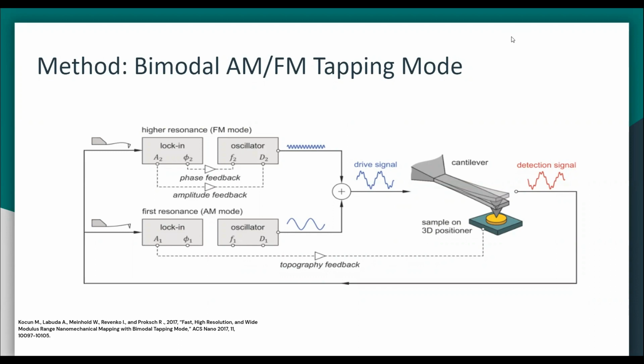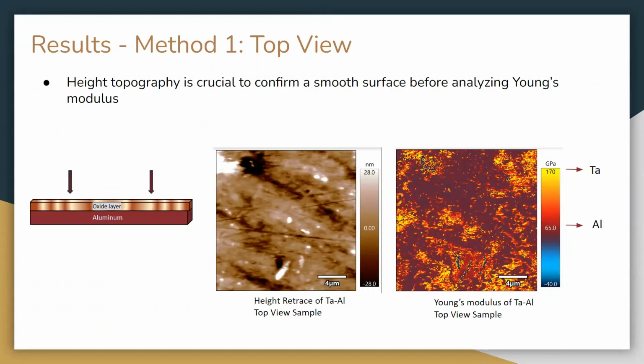So the first method that I looked at and sample that I looked at was a tantalum aluminum substrate material sample. And what I was looking at was the oxide layer on top of the aluminum from a top view perspective, so a bird's eye view. And as a result, I looked at the height topography as seen in the height retrace because it's crucial to confirm its smooth surface before analyzing the Young's modulus. And then on the right is the Young's modulus of the sample.